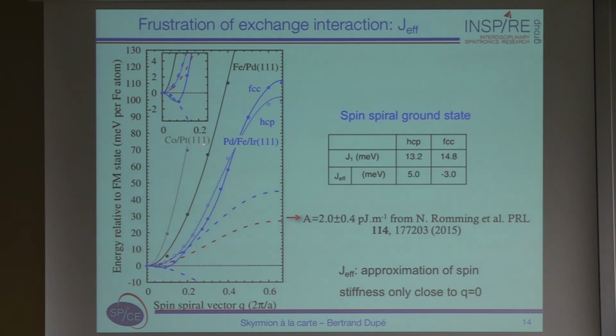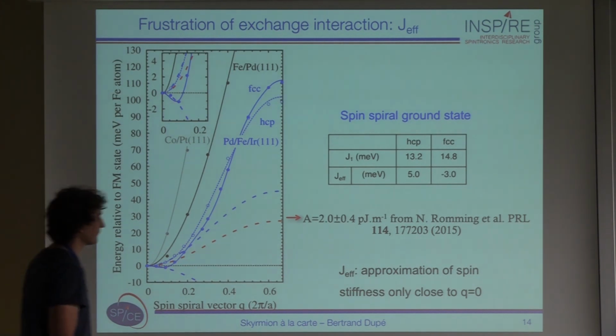And as a comparison, I show you a system where you have absolutely no frustration. The cobalt platinum is a purely quadratic system. It's a strong ferromagnet. Here, this is a purely quadratic curve. So you don't expect any difference here between J1 and J effective. And you see that our systems here are quite far from this case.